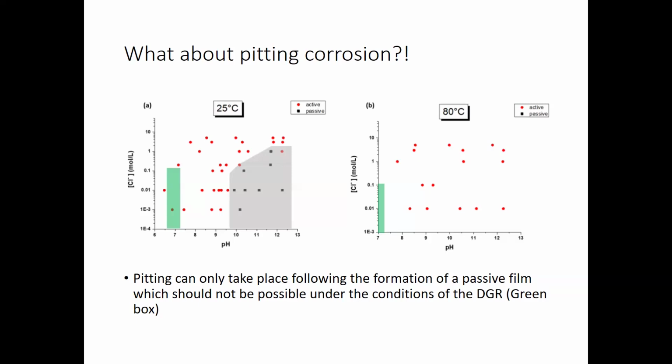In this case, though, we're dealing on the time scale of 1,000,000 years, and so relying on a passive coating is a very, very bad idea under these conditions. You want to maintain corrosion in an active but small, uniform state, in order to properly account for the amount of corrosion your container is expected to withstand. Once you have pitting corrosion, all those estimates go out the window, because if it goes through the copper, as we'll talk about in a sec, galvanic corrosion can begin, and you quickly have issues.